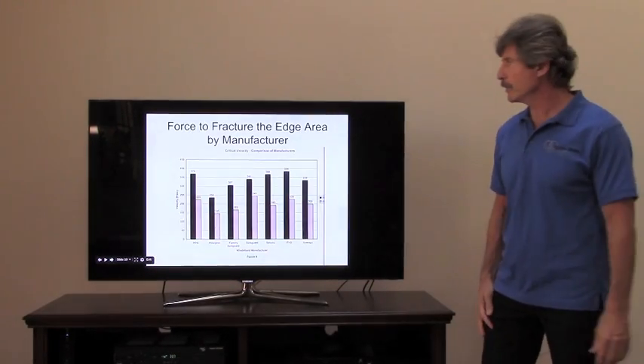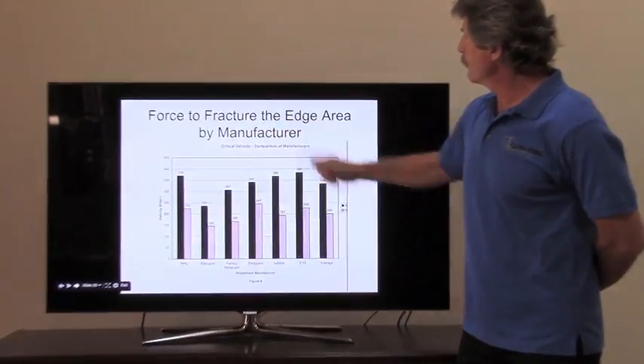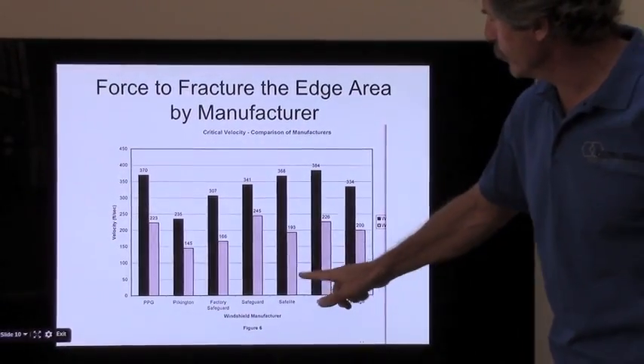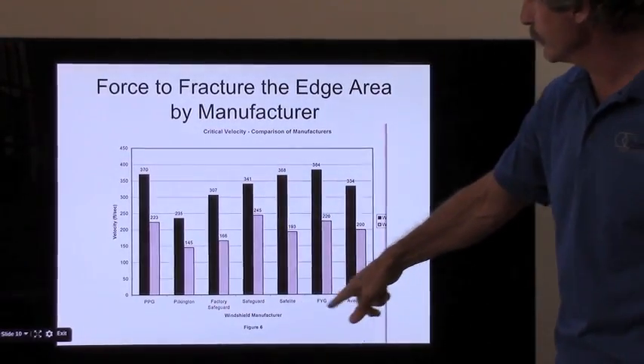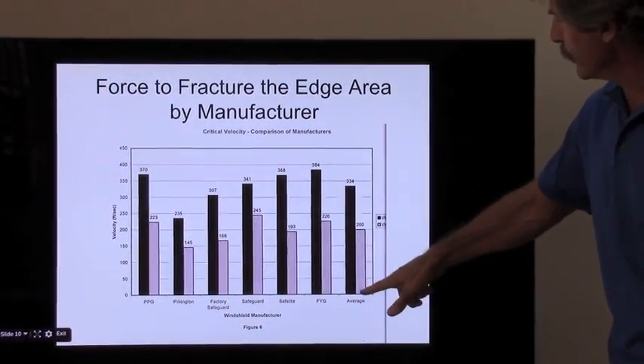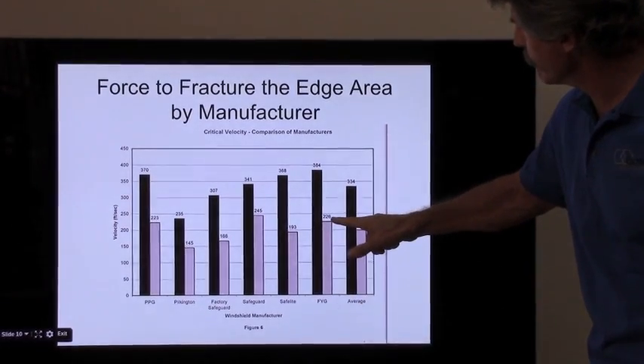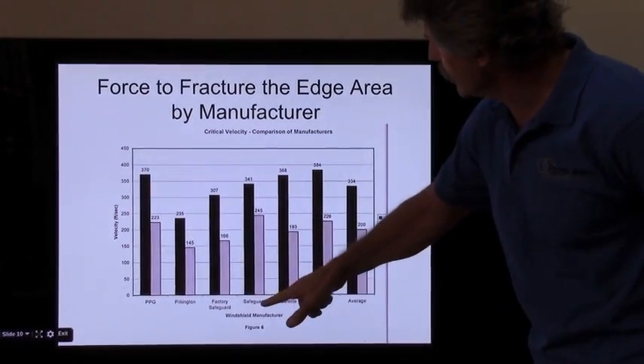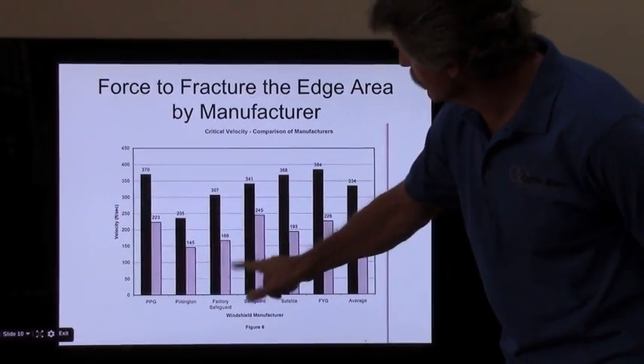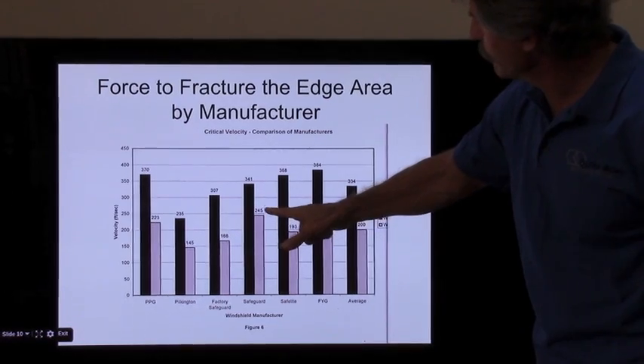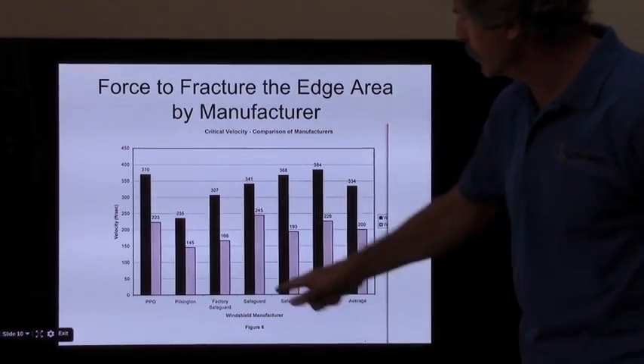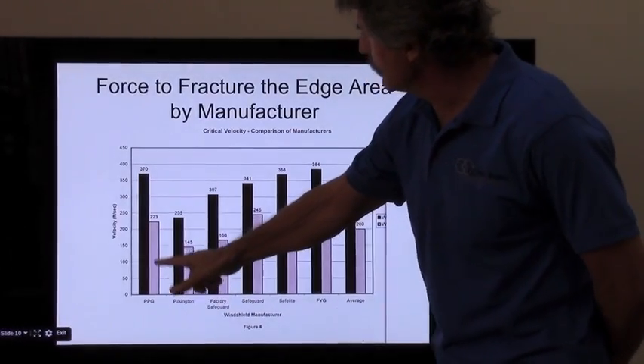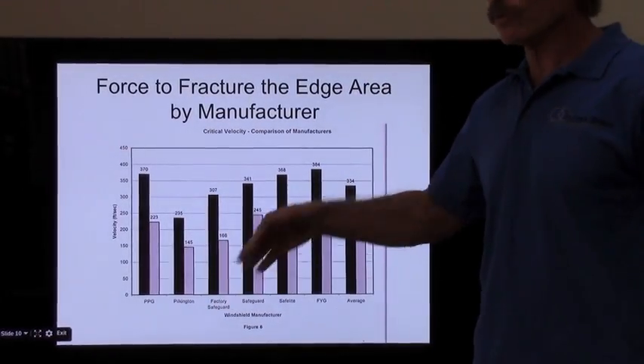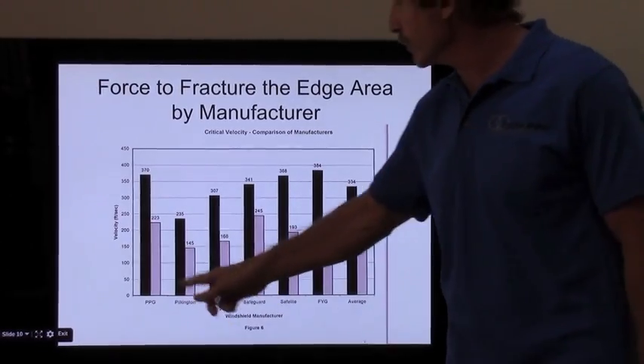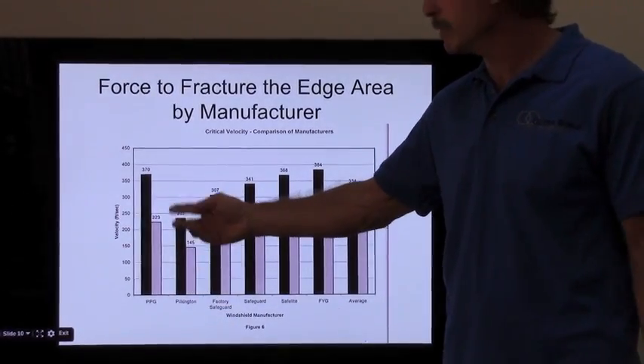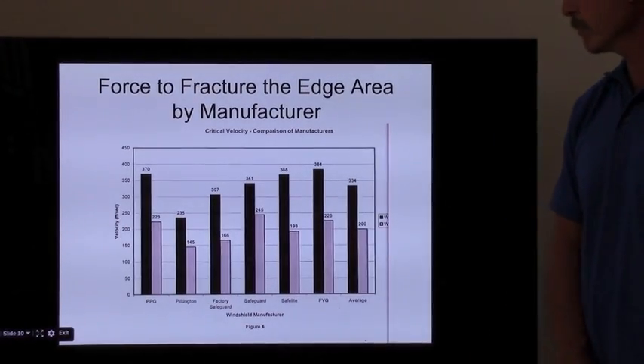But here's what was on here. This was the force to fracture the edge area, and we had, see, 1, 2, 3, 4, 5, we had 6 windshields, 2 of them are the same. And this was the force to fracture the edge, and the Chrysler Safeguard, their OE, that was the factory one, and that was their aftermarket one, which is one and the same actually, because they don't have aftermarket of that brand, and Pilkington and PPG. Now this was one windshield. This is not real accurate because if you were to really test this, you'd have to test anywhere from 3, 4, maybe even 10 of them to get more accurate data.